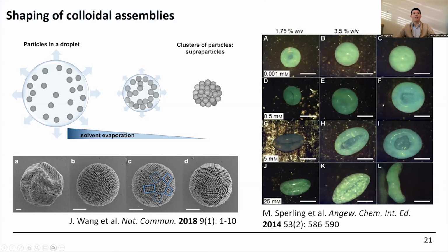Then in the end, they won't end up with the spherical shapes. Instead, they will have these anisotropic shapes. And the anisotropic shape is very interesting for us because we are working on microrobots, because the asymmetric shapes will give us efficient motion. But with this shape, it's hard to control, because the end structure is not that controllable. And we want to have better control of the shapes.